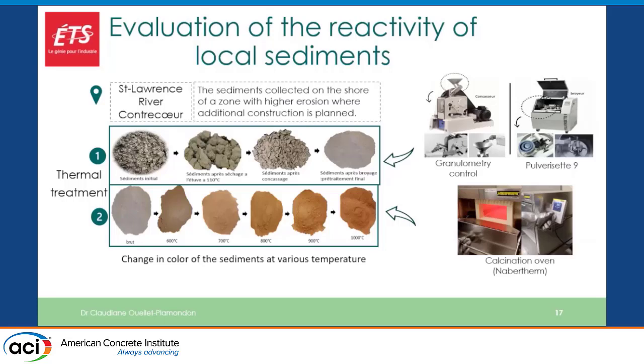And so far, our results are very promising because it looks like the raw material that is not calcined is performing better than the one calcined at 1000 degrees. And even there's not a very big difference between the raw material and those that is calcined at 600 degrees Celsius. So for that reason, it's very likely that we'll go with the raw material, and then we're trying to find out what is the percentage replacement that we can do. And eventually, we will try to also include our printability requirement to find the proper printability mixtures.